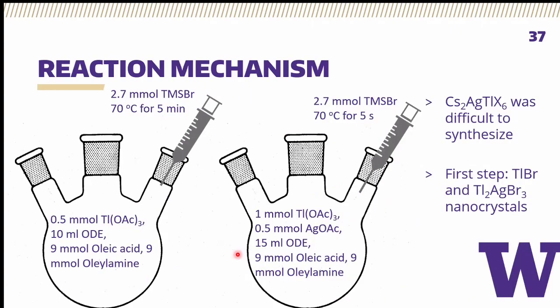Cesium silver thallium bromide synthesis was not as easy as just taking the bismuth out of the Gamelin reaction and adding thallium back in. So to work up to making cesium silver thallium bromide, we started with just trying to make thallium bromide nanocrystals, worked our way up to thallium silver bromide nanocrystals, and then hopefully achieve these CATB nanocrystals we were really hoping for.